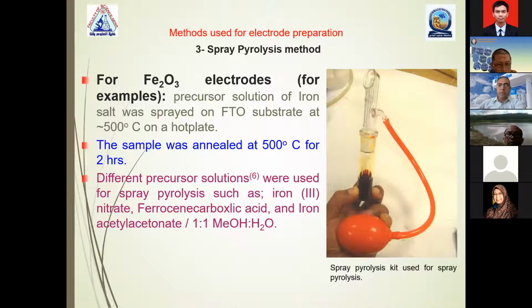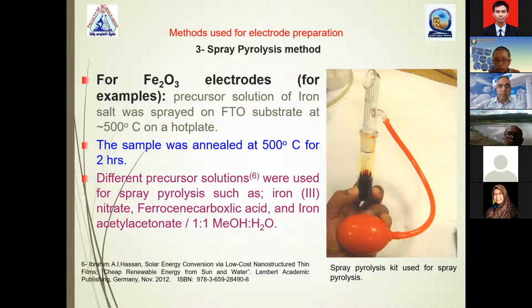Another very simple method is called the spray pyrolysis method, and it's a very simple kit, like a spray bottle pyrolysis kit. For example, if we want to prepare an iron oxide electrode, we use a precursor solution of an iron salt, any salt like iron nitrate, trivalent, dissolved in 1:1 methanol and water, and then put it in this small bottle. By pushing the rubber we can spray very small droplets, which make nanostructured iron oxide, especially by annealing and producing crystals of iron oxide nanostructure.